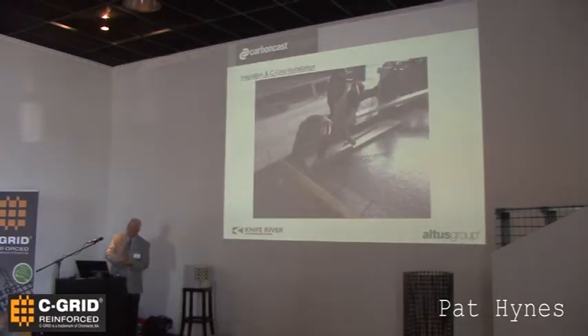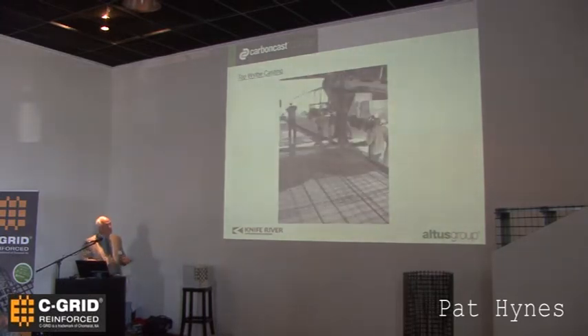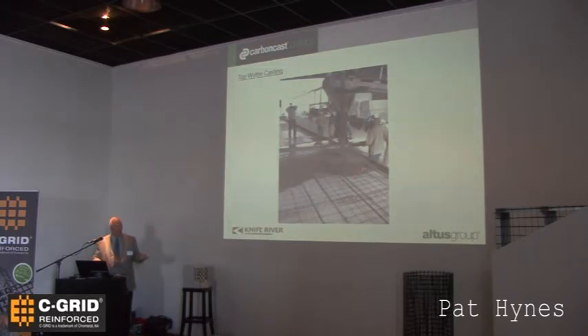If you put a piece of insulation next to concrete, it will have some shear transfer capability, as long as you have it clamped together. So there is a three-part mechanism, and it's all been tested. Here it is on the second pour; the first pour's been down. One thing that amazed me is the embedment minimum. We don't want to go less than half an inch, but we try to get 3/4 here, 20 millimeters. That surprised me too, how little we needed.